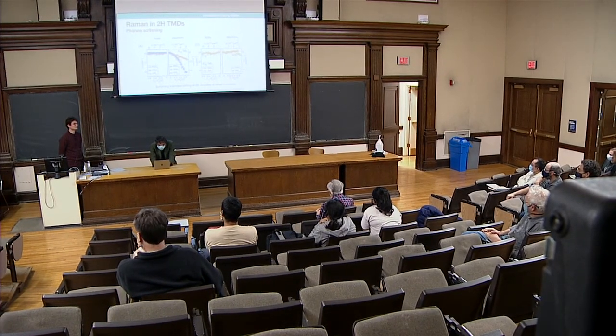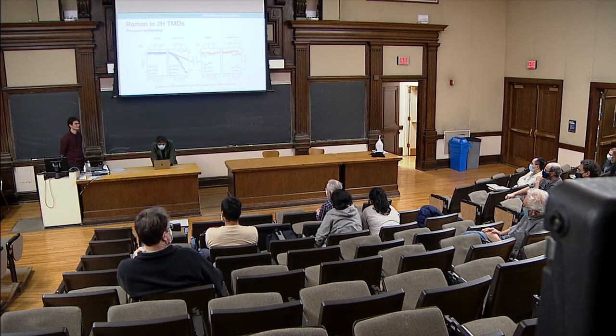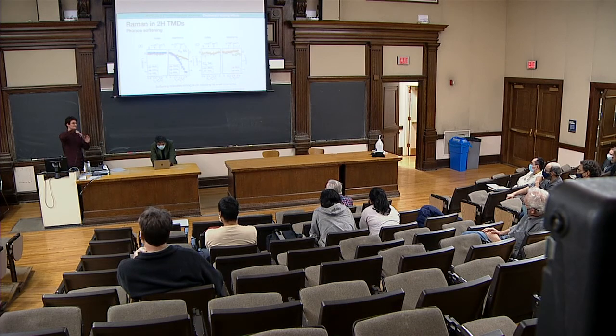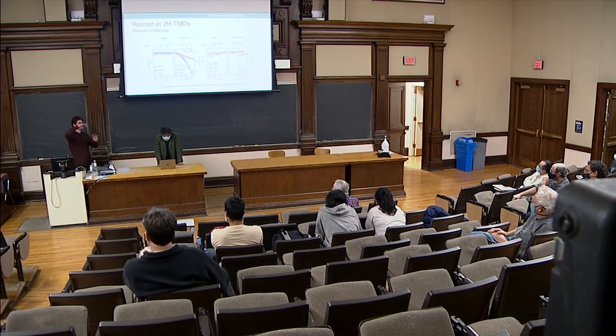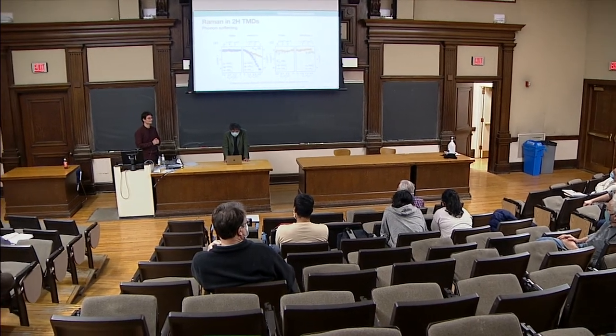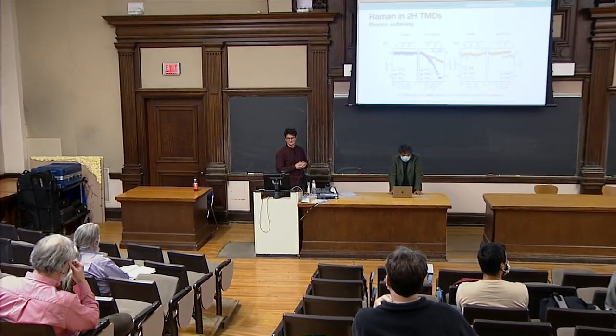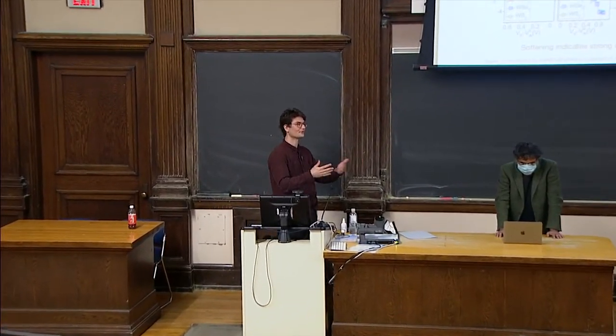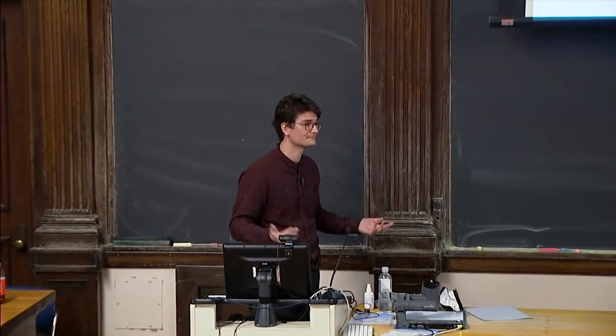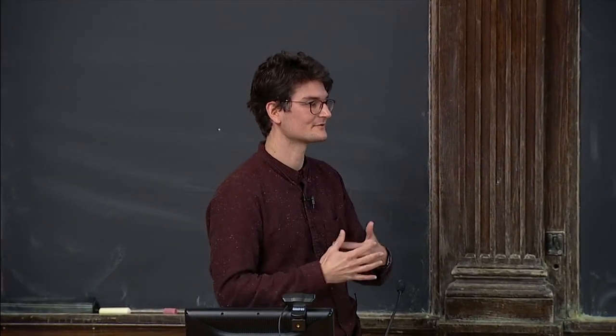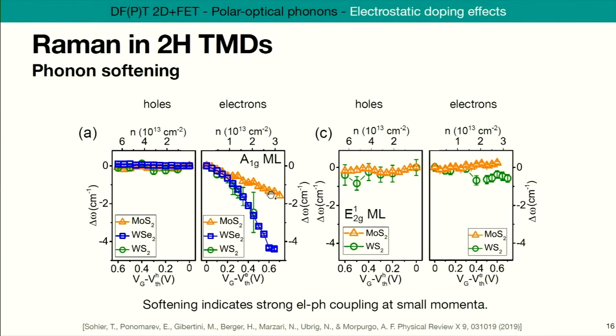Those experiments are at room temperature, so we're talking close, plus or minus 30 meV, the room temperature energy, because the Fermi distribution is smeared by the temperature, more or less. The DFT varies between a few dozen meV to 300, so you have this order of magnitude. But from those experiments, one can maybe argue that this orange one is a bit further away, and it makes sense. In DFT, we have the same ranking. But those two here are probably very close, within 0 to 50 meV.